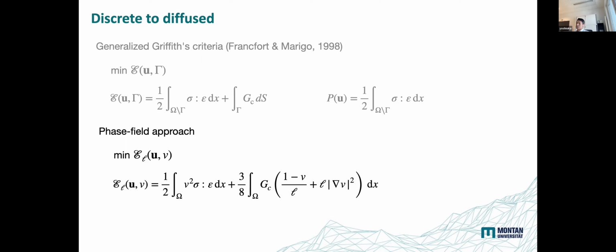And with the phase field approach, this energy minimization problem is regularized. It is replaced with this continuous problem. The first term, the mechanical energy, was a discontinuous integral. The stress or strain is discontinuous over the crack gamma. We could not integrate over the gamma, but using this phase field variable D, we can take an integral over the entire domain omega. And the second term, the surface energy, was an integral over the discontinuous surface, which is difficult to evaluate. But by introducing the phase field variable D, this also becomes a volumetric integral.